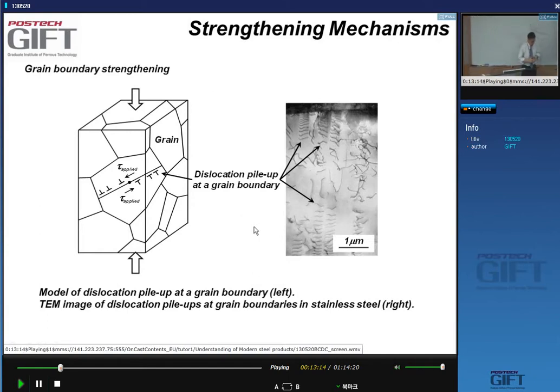Now, dislocations themselves interact with each other. They interact with the point defects, and they will interact basically with any other thing that's on their glide path, and obvious obstacles are grain boundaries, because there is a discontinuity in the crystal structure. Basically, the crystal structure stops, and you cannot propagate these dislocations across the grain boundary. So they tend to accumulate, and form pileups.